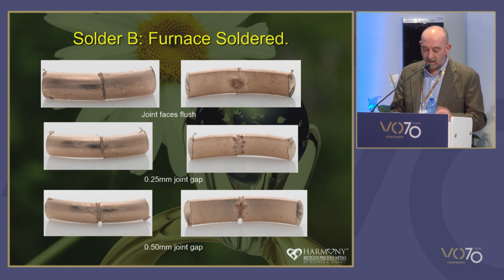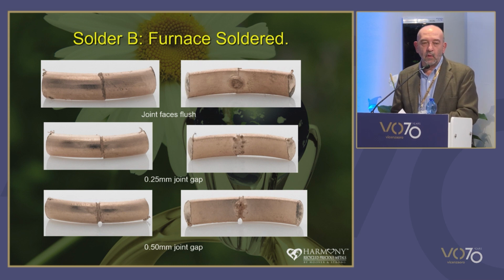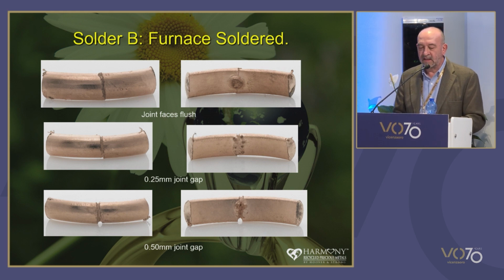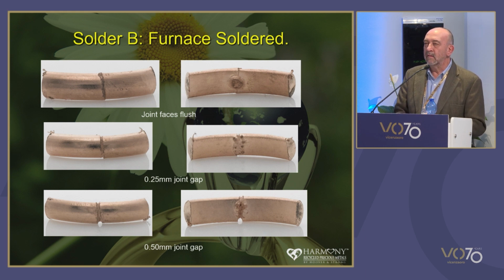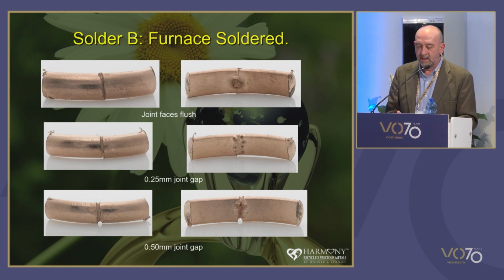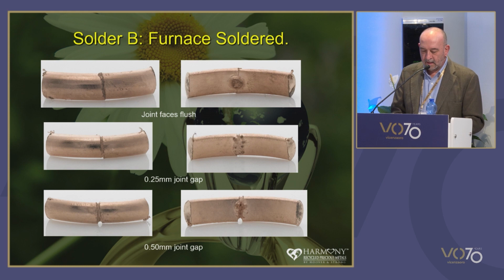As with the wetting tests, like I said, solder B had evidence of the residual solder being present, and it had very poor wetting and very poor flow. All the other tests were acceptable, but needed repair to achieve an acceptable standard. Overall, hand soldering was far more forgiving than furnace soldering, giving consistent results. This doesn't mean that these solders are unsuitable for soldering in a furnace. It just means that significantly more effort needs to be made to set up the furnace. You need to set up temperatures and belt speed and dial it in for your particular application.